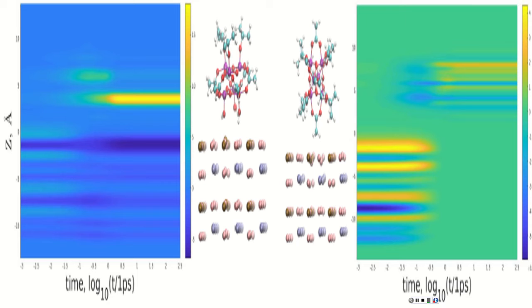transient charge transfer. By the way, it is similar to what Dan computed for your recent work. So a transient short period charge transfer. And then later, the lowest excitation, both blue hole and orange electrons, stay on the acceptor. So the final state is neutral. But if we allow this structural change by replacing isopropanol with hydroxyl, we start with both electron and hole originally on titanium dioxide, and then the hole stays on the perovskite slab, and the electron jumps to titanium dioxide. So just a little chemical tweaking of the linker makes a drastic change in the quality.